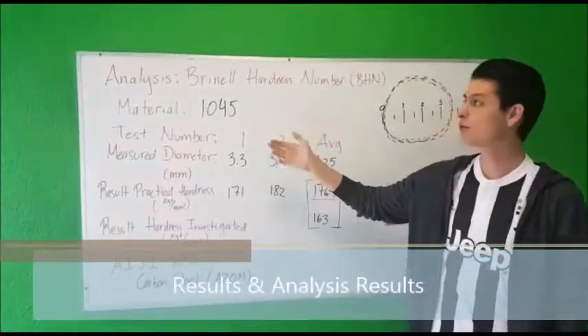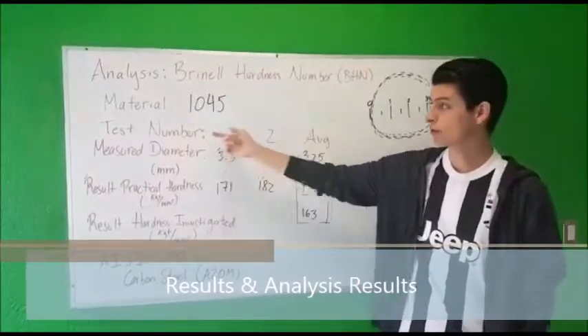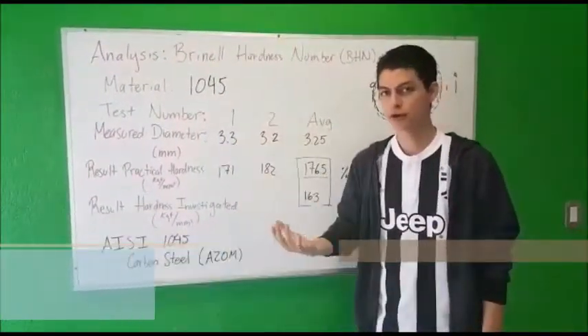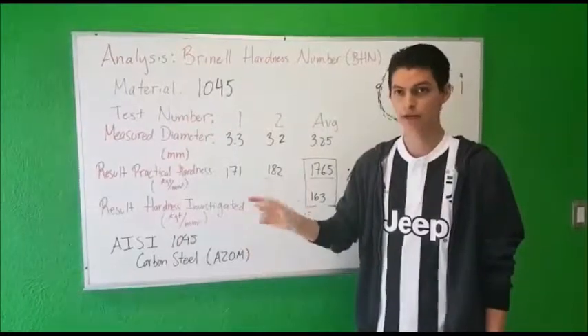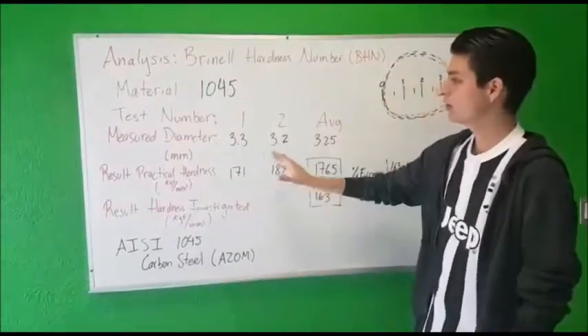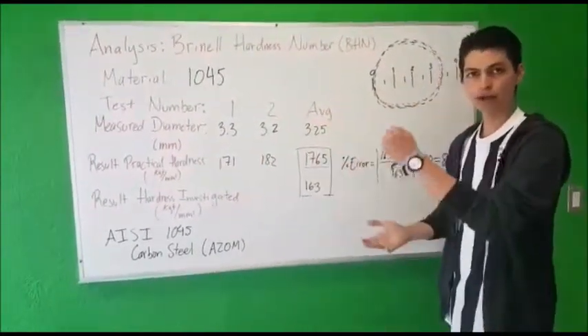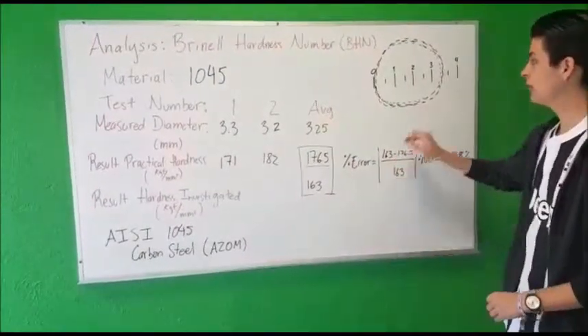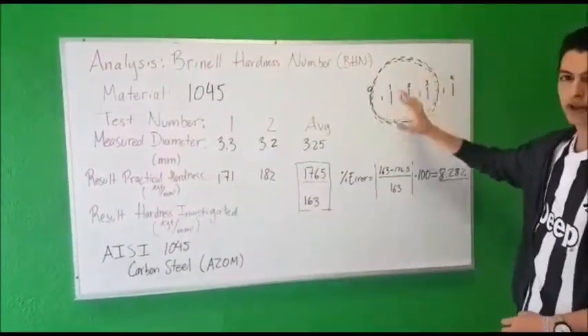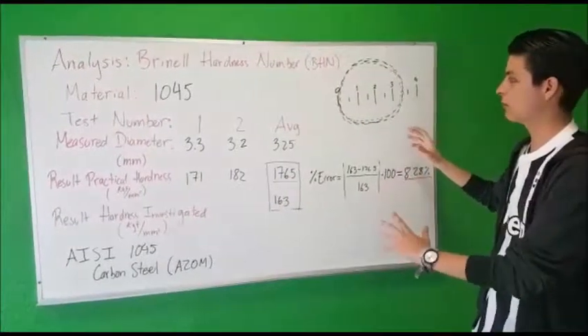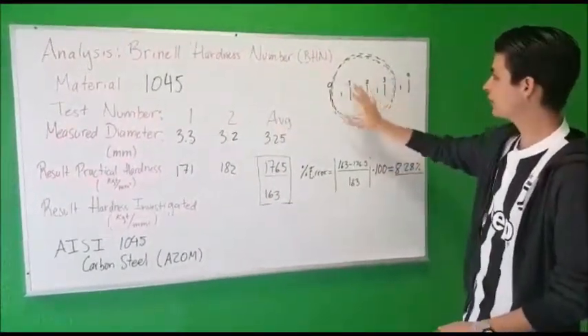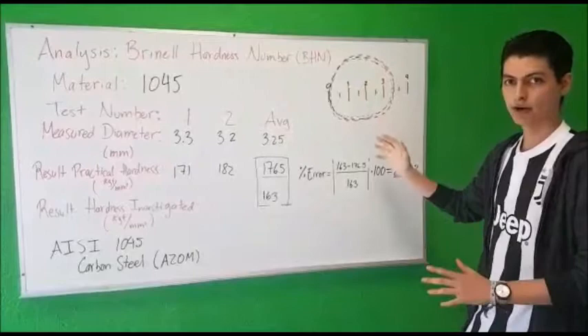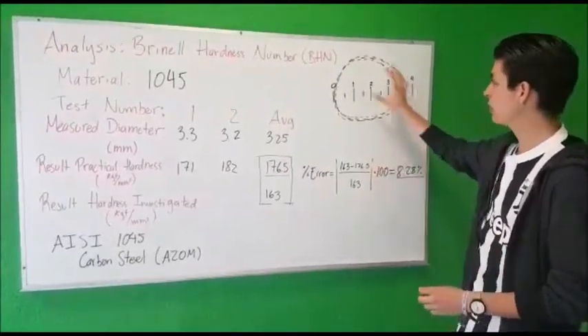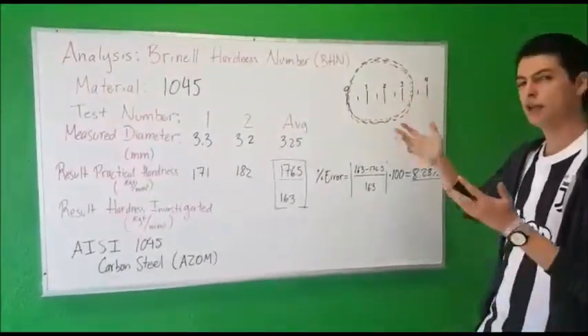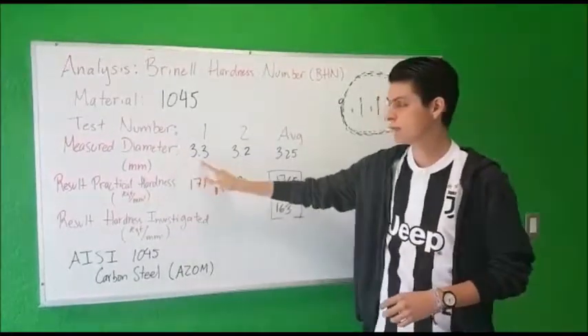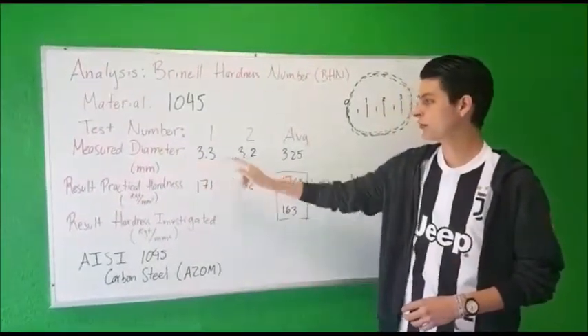The first analysis we have to do is a Brinell hardness number for the 1045 steel, in theory the stronger metal of the two. After applying the force with the ball, we ended up with a shape almost like this in the 1045 steel, and we had to calculate the diameters. We did this 2 times, and we ended up with a shape like this. So we estimated the measured diameter. We have 3.3 and 3.2.